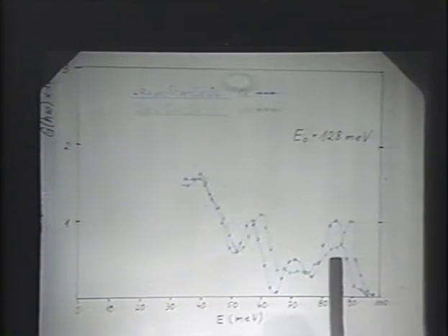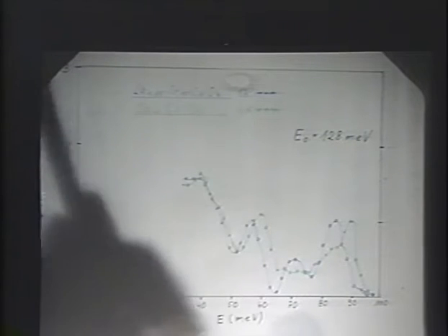And this is the most pronounced effect that we could have measured. One sees that these interplane modes and breathing modes here, the high frequency ones, are pronouncedly shifted to lower frequencies for the superconductor, just as well as these modes here are shifted to lower frequencies. I want to remember the talk Schlesinger gave, that he saw at 60 millivolts strong coupling to the electrons, and we see also an effect going from the non-superconductor to the superconductor.